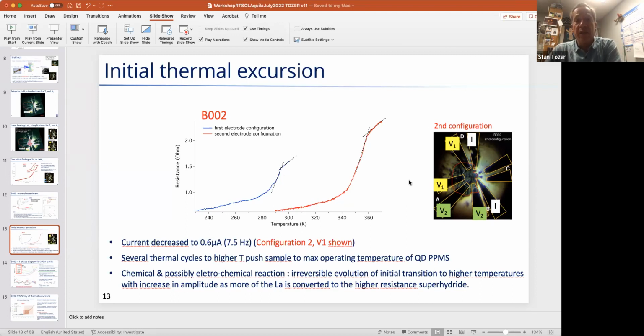The configuration that we're looking at is this second configuration here, where the current is across the extreme electrodes that are in touch with the sample, and then tapping into V1B1 here and looking here. And again, we're seeing the same transition, and it's in a different region. The first one, the blue, is this region here. And now we're seeing this same interesting material in the region above it, okay?